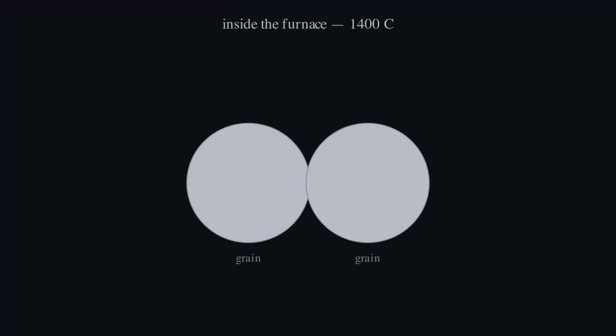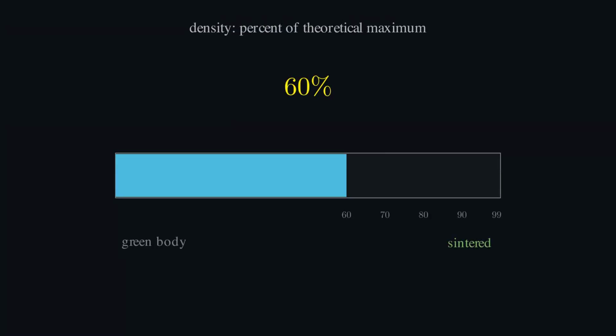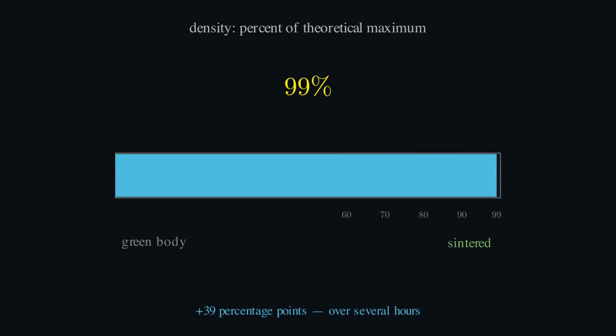Inside, at 1400 degrees Celsius, something slow and remarkable is happening. The grains are not melting. Ceramics with strong covalent bonds barely melt at all. Atoms creep, one at a time, across the boundaries between grains. They fill the pores, they fuse the necks. After several hours, the green body has shrunk by about 20%, and reached 99% of theoretical density. That is sintering. Powder made into pottery, by diffusion, below the melting point.